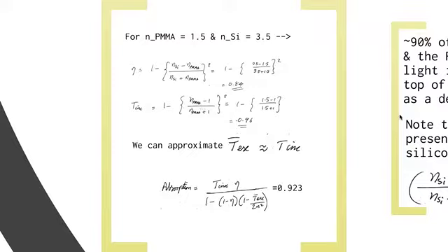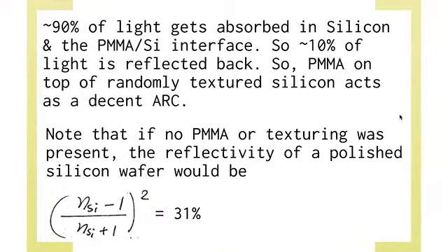That means 30% of the light on bare silicon will simply get lost. Won't even enter the cell. Here you reduce that loss to about 10%. This is quite nice. Very important. So just to put this into words: 90% of the light gets absorbed in silicon at the PMMA-silicon interface, which is what you want. About 10% of the light is reflected back. So PMMA on top of randomly textured silicon acts as a decent ARC.